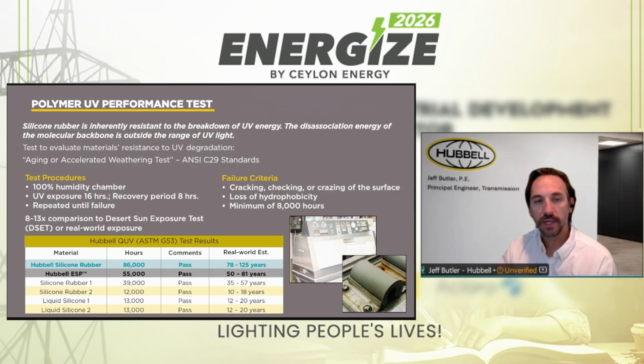So we took plaques of rubber, put them inside this chamber, and tested them until we saw some sort of failure. And the failure criteria was cracking, checking, crazing of the surface, basically a breakdown of the polymer itself, extended loss of hydrophobicity, and then our threshold was a minimum of 8,000 hours. So we took our Hubbell silicone rubber, our Hubbell ESP, two other silicone rubbers, and two other liquid silicones, and we performed the test. Successfully, all of them did pass the 8,000 hour minimum, but you can see there that the Hubbell materials far